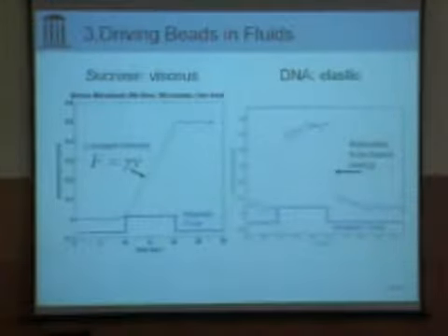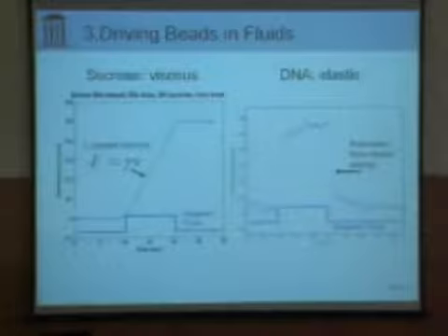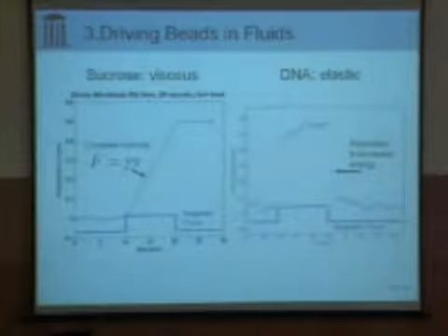Here's two examples of fluids at the extreme. If you take water and you pull on a bead, you'll turn on the force for a time and then you turn it to 0, the bead moves uniformly. Stokes' law. And when you stop the force, the bead just sits there because no force is applied on it. In a material which is elastic, you turn on the force, the bead displaces, and then it stays relatively still. You stretch the spring, you've stored energy in the material, you turn off the force, and the bead returns to its original location. That's an elastic material.